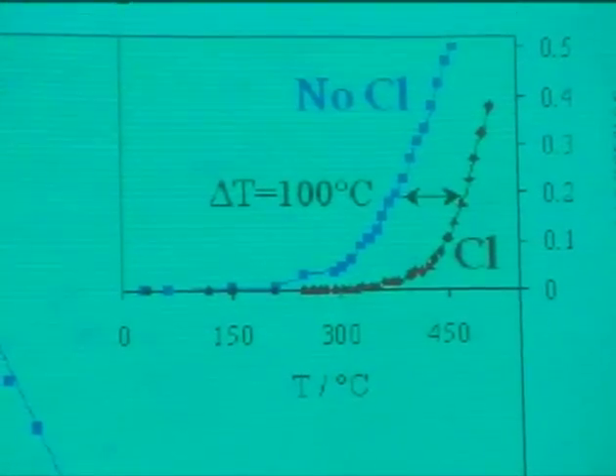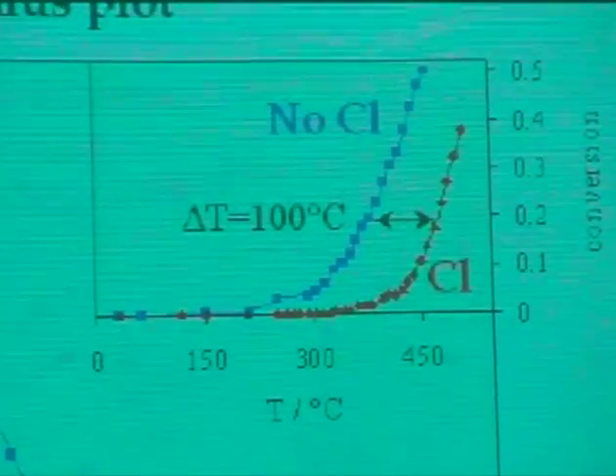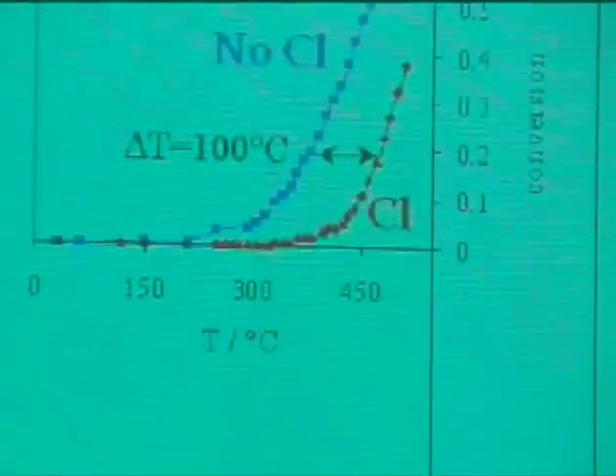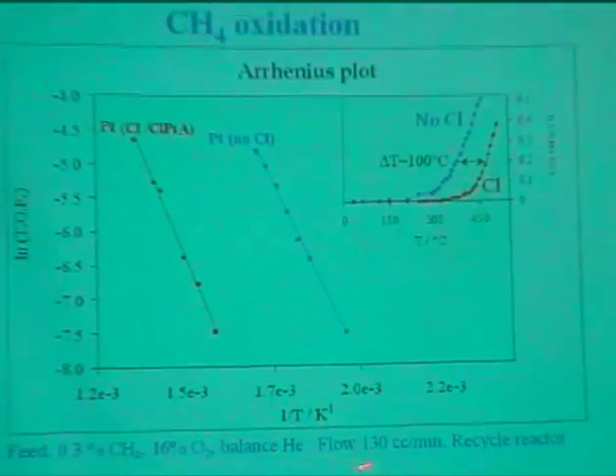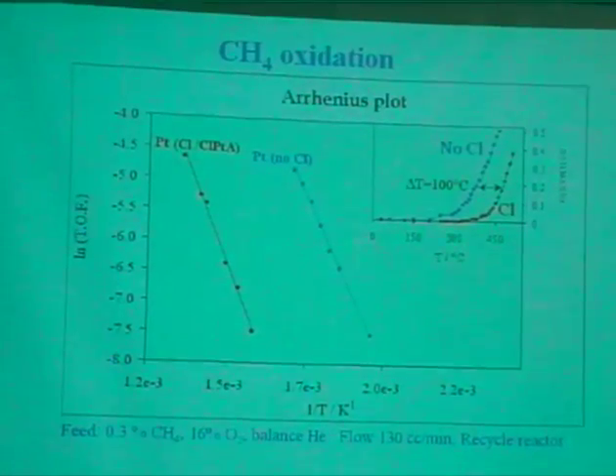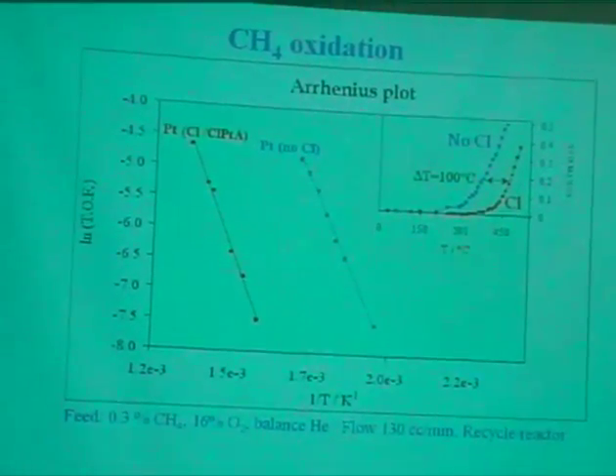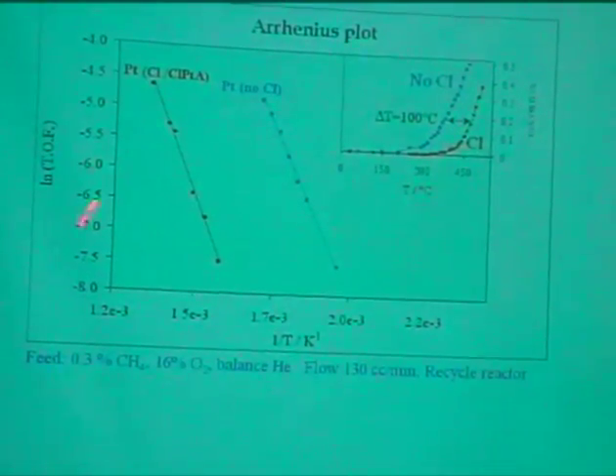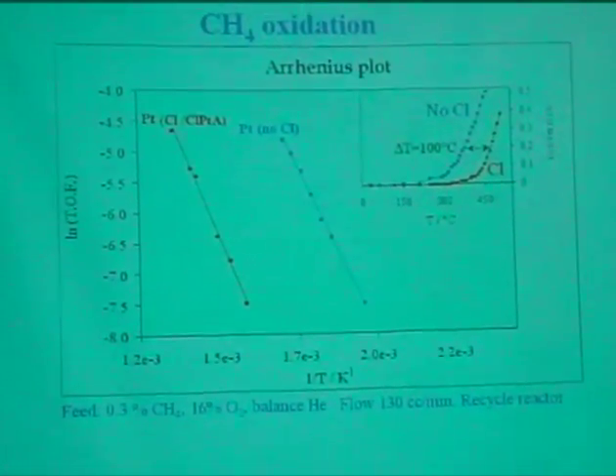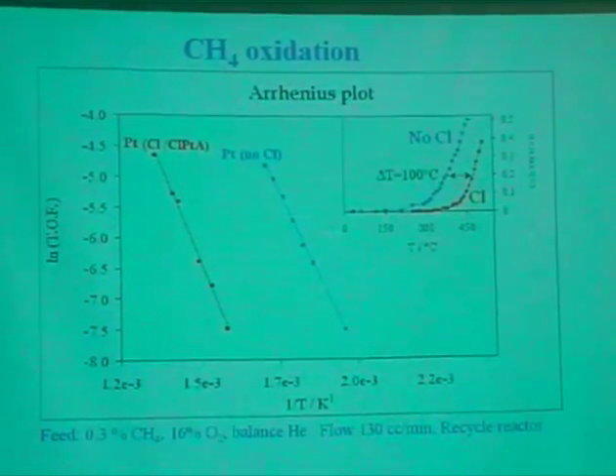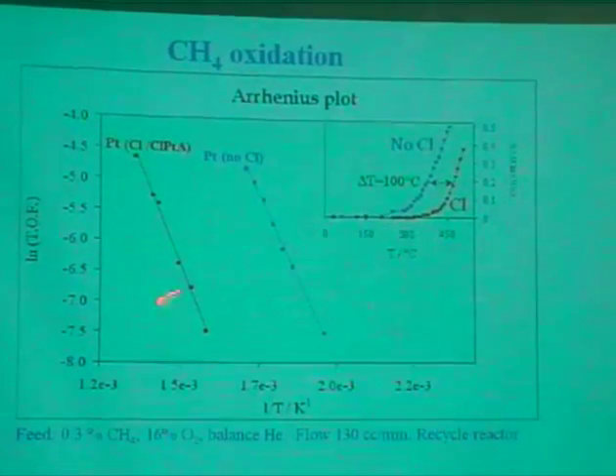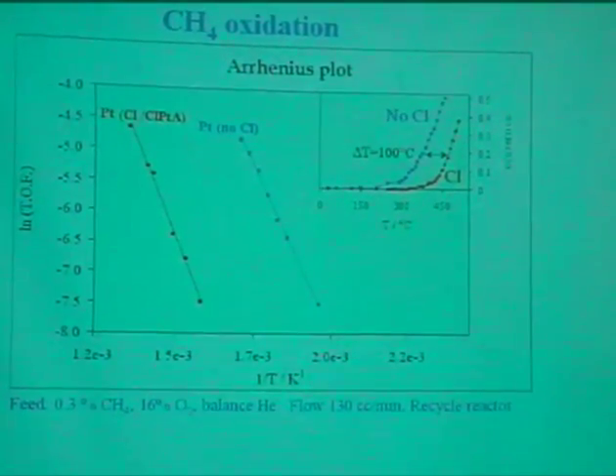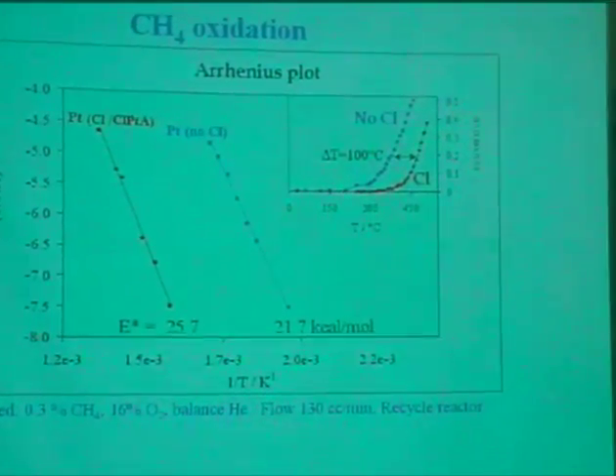Now here there is a significant temperature difference between the two catalysts. I should also mention that we use a very dilute feed so that we don't introduce the effect of carbon, but if you use higher carbon concentration, the results also change. It's an oxidizing environment. This is the standard flow rate on the reactor, but there's a recycle ratio of 20 so that we can calculate rates as in a CSTR, and we normalize those with the initial area that we measure at room temperature, and we have activation energies here that change a bit, but not too much.